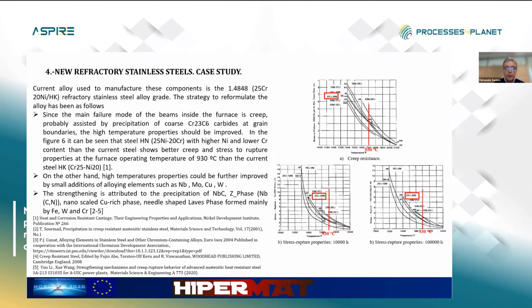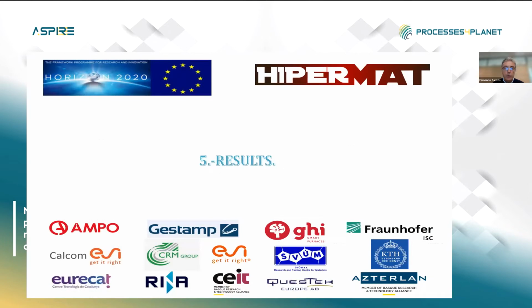When we studied the different qualities of different types of alloys used in the industry, we took the more standard alloy as reference, and we studied how the different chemical elements, the process, and the phases affect these materials. We made quite a complex study supported by different partners, and in the end we checked that higher nickel contents improve the properties, and other chemical elements improve them by minor additions like niobium, molybdenum, copper, and tungsten. And we also checked why this happens, and this is because of the precipitation of different phases or the formation of others. So this has been the way of working. We'll go on to the results.